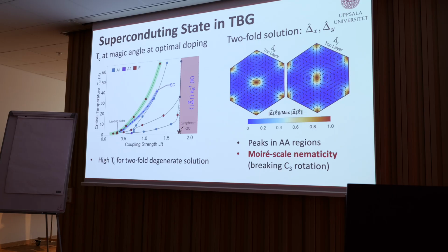And you see, I have a lot of order parameter in the AA region, as I expect. That's where the electrons live. But it also clearly has broken rotational symmetry. Remember, the normal state had no broken symmetry, so this is a superconducting state that breaks the symmetry. So this is a moiré-scale nematicity I get in the sample, as for looking at which solution is best.